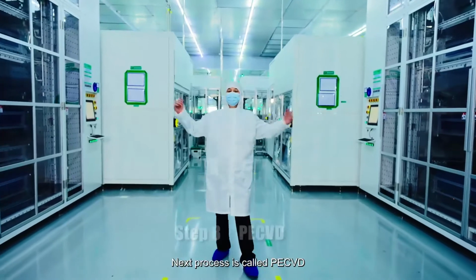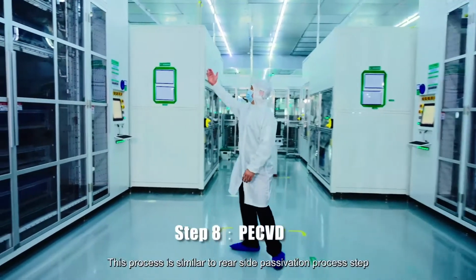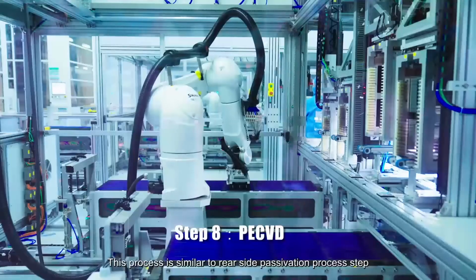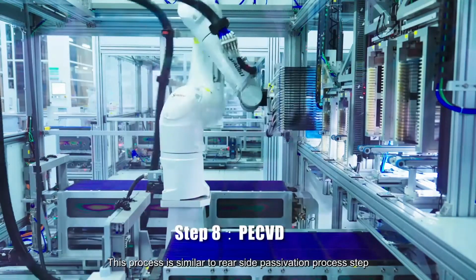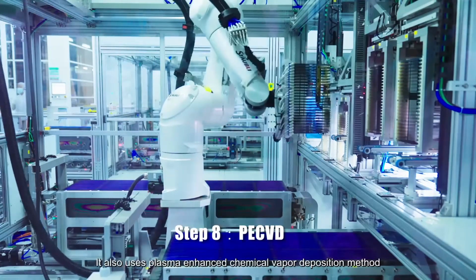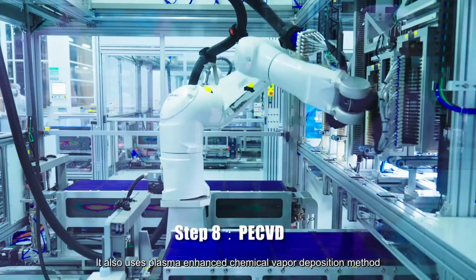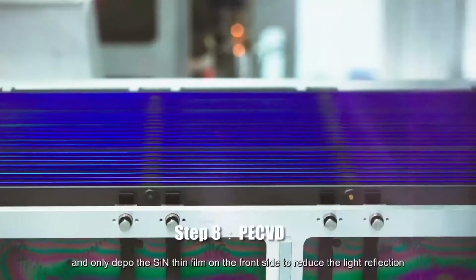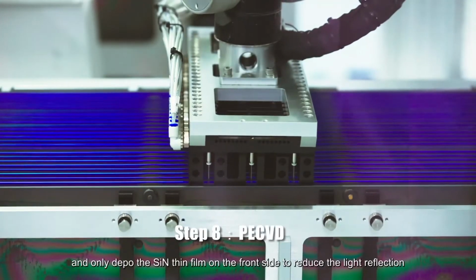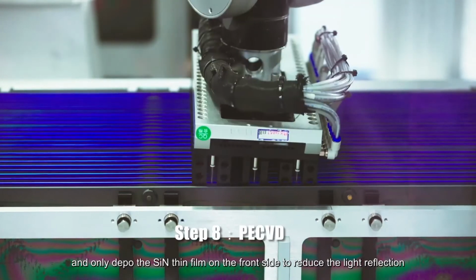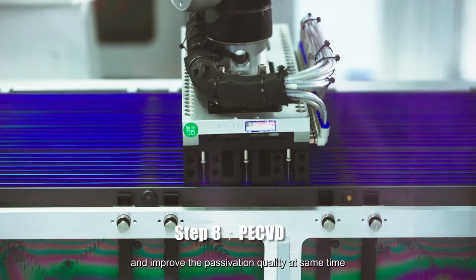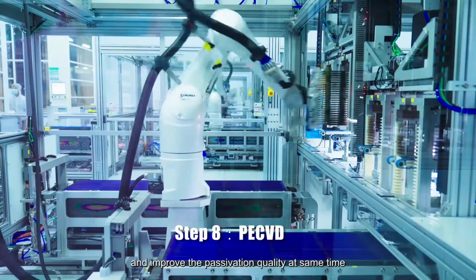The next process is called PECVD. This process is similar to the rear side passivation process step. It also uses the plasma enhanced chemical vapor deposition method and only deposits the nitride thin film on the front side to reduce the light reflection and improve the passivation quality at the same time.